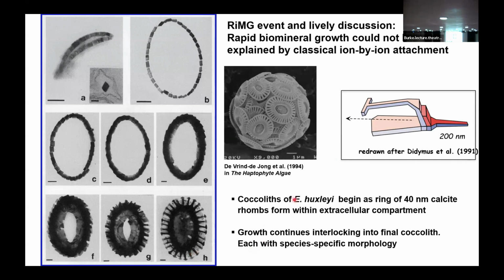And so here's a great example where you have a coccolithophora. This is a phytoplankton calcifying. Each one of these platelets, these are seen by SEM, starts off as a wreath, if you will, of 40 nanometer rhombs of calcite. So they're nucleated and grow to 40 nanometers. And then, as determined by the biochemistry that's local to that setting for that species, they differentiate into different morphologies, depending upon the species, into something like this. And you'll see this in the book.